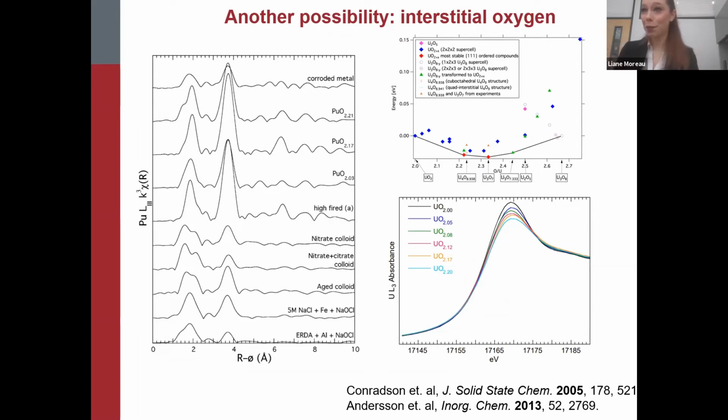So these are things that can both possibly complicate the process, but there has, at least in the case of bulk species, been a body of work that has already accumulated related to higher oxide incorporation based on oxidation processes within uranium and plutonium. A lot of that work was pioneered by Steve Conradson. If we take a look at those types of systems, we can see that uranium has a tendency to form oxidation at surfaces that follow an oxygen incorporation model, where the oxygen would incorporate into interstitial sites. So this is something else that we would potentially need to look into in the systems we would be looking at.